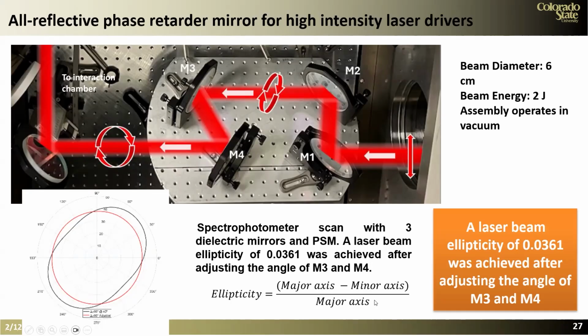We obtained an ellipticity of approximately 0.0361, which is very good. It tells us that we made circularly polarized light. So the idea here is, if we cannot use optical elements, let's use mirrors to play all these tricks and be able to propagate very high intensity laser beams.